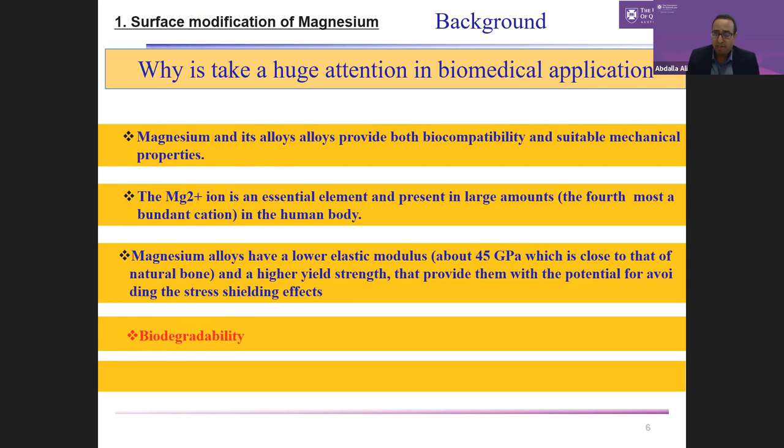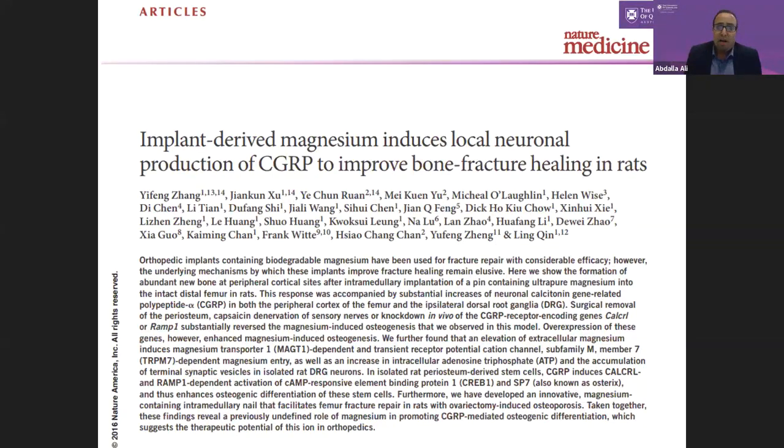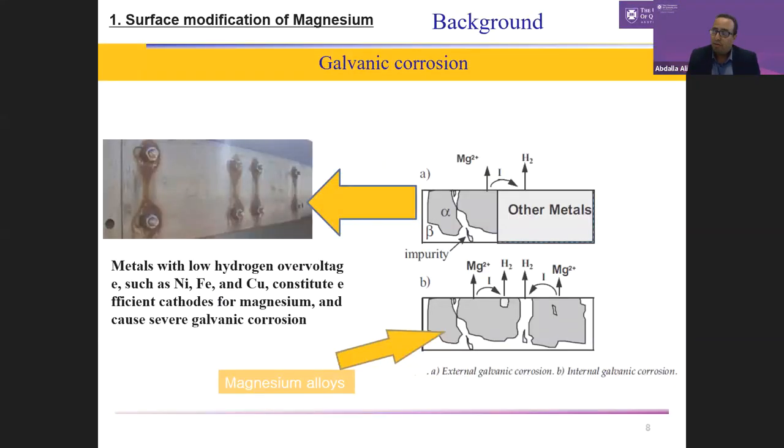Biodegradability is a more interesting characteristic, the biodegradability and bioresorbability of magnesium. Magnesium shows excellent osteogenic properties in early bone formation and interaction with the surrounding bone, and this paper, published in Nature Medicine in early 2016, showed how magnesium can stimulate the gene factors responsible for osteogenic properties. So the main issue I will share with you is the high corrosion or rapid degradation rate